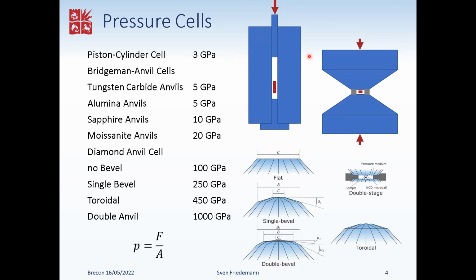Anything beyond that is based on the Bridgman Anvil type, so taking 2 anvils where we focus some force on a small area, and we're pretty much really playing P equals F over A. If we want to have a larger pressure, we make the area on which we focus the force smaller. Between these tips of the anvils here, the flat tips, that's the culet of the anvil, we place a gasket, which then seals off a volume in which the sample lives. And again, we try to use a pressure medium that ensures as good conditions, hydrostatic conditions as possible, but I'll come to that later.